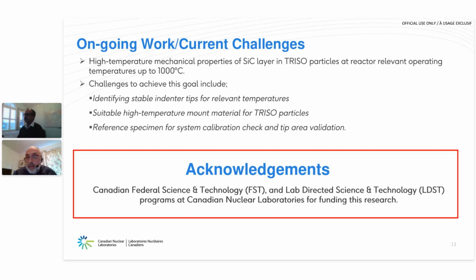That's a very good question, Alex. All these measurements were made exactly in the center of the coating, or relatively in the center of the coating. The coating was about 40 microns wide, so about 20 microns from either edge. But we do plan to look at the variation of the properties from one edge to the other, where, as I was showing, there is a difference in the grain sizes: smaller grain size near the inner pyrolytic coating layer, and as you go towards the outer pyrolytic layer, the grain size becomes larger. So we do expect to see some changes, but we haven't looked at the results yet. But that's part of the plan.